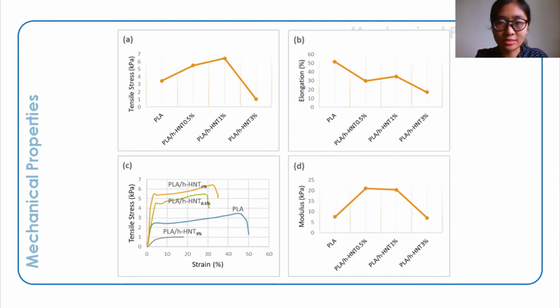So a wound dressing material needs sufficient tensile strength and elastic property to withstand stresses exerted by body parts, subject to distortion or movement, and able to contour to the topography of the wounded tissue. Hence, tensile strength and modulus can be connected to the conformability of the wound dressing material. The tensile strength and modulus of 1% HHNT content were observed to be the highest and most favorable reinforcement for the polymer matrix. Hence, the reinforcement of hydroxylated halloysite slightly enhances tensile strength and modulus initially at 0.5% and 1%, and then diminishes as clay content increases, as what's seen at 3% HHNT content.